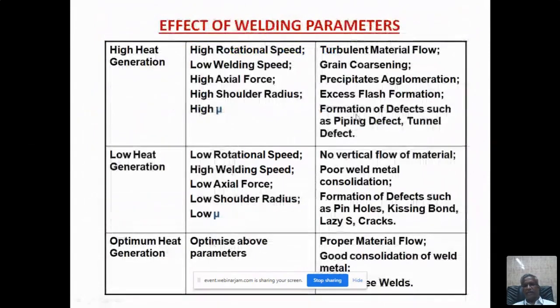Then there are other defects. For aluminum alloy and magnesium alloy in fusion welding, TIG welding, MIG welding, they produce a lot of defects: solidification related defects, hot cracking, alloy segregation, partially melted zone, porosity. These are the defects in fusion welding of aluminum alloys or magnesium alloys. But in FSW, friction welding, those solidification related problems are completely eliminated because there is no melting here. It is a solid state welding process. Welding takes place well below the melting temperature.